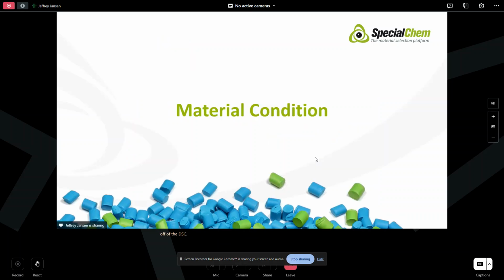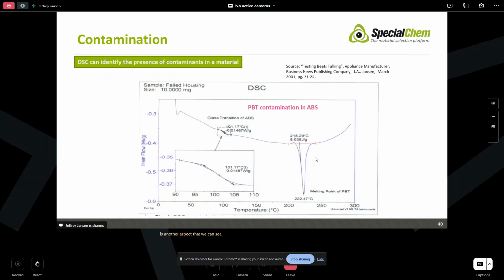Material condition is another aspect that we can see. One of the things that DSC can do is identify the presence of contaminants in a material. So here we have PBT contaminated in the ABS, and this is a great example of the variation in the intensities of melting endotherms versus glass transition. And here we see that the PBT is a contaminant. What we ultimately figured out is it's about 20% PBT. There was a lot of contamination, but you'd never guess that if you looked at this result.